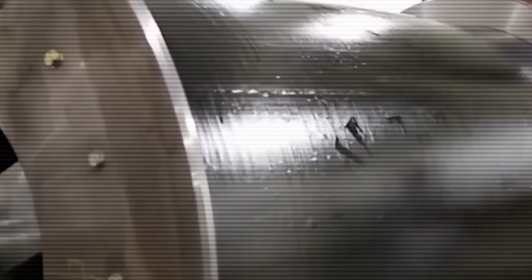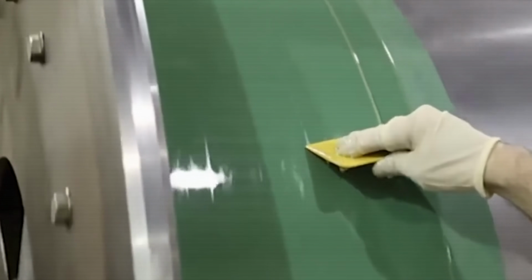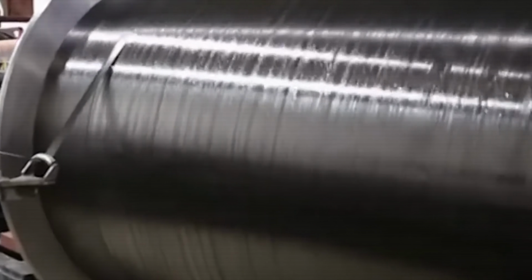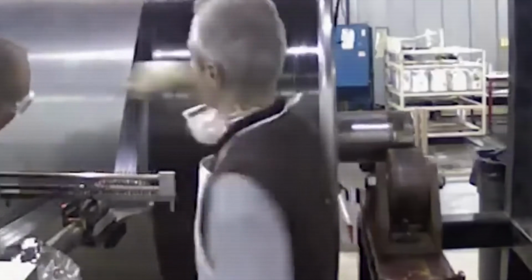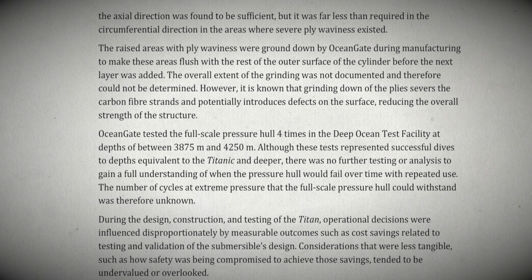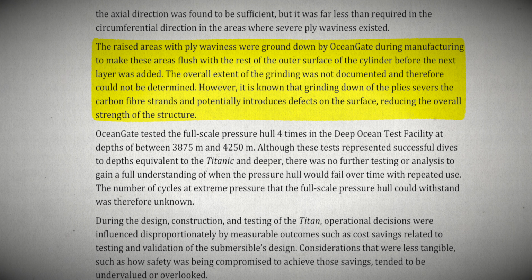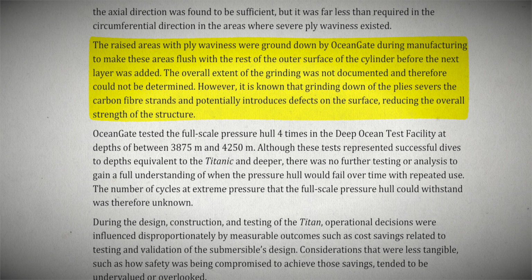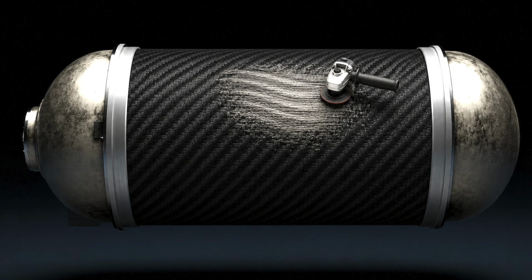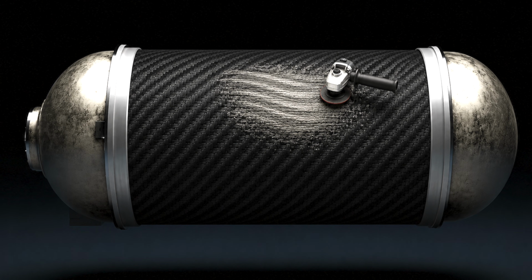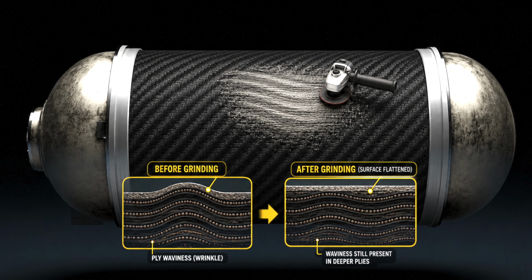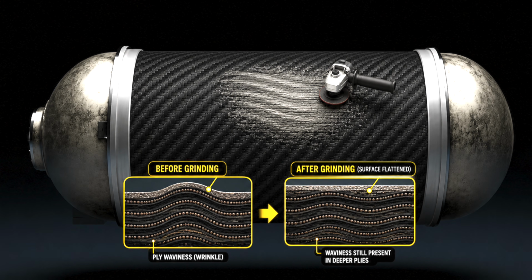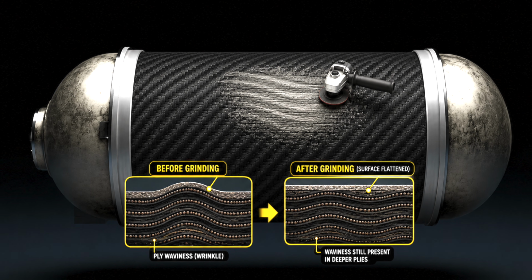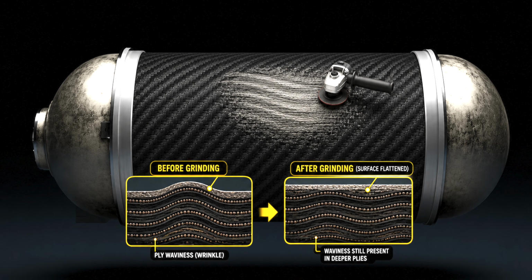In addition, during fabrication, sections of the carbon fiber developed wrinkles where the fibers buckled instead of remaining straight and aligned. Because composite materials derive much of their strength from continuous, properly oriented fibers, these wrinkles significantly reduced the laminate's structural efficiency. OceanGate attempted to correct these defects by manually grinding the wrinkles away. However, the investigation found that this repair often displaced the distortion into the adjacent layer rather than eliminating it entirely. In some samples, investigators identified as many as 12 ground repair locations, suggesting that correcting one defect frequently created another deeper within the laminate.